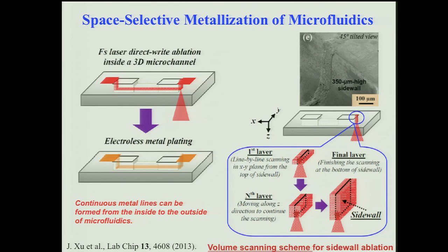We also developed a technique which can perform the space selective metallization of the microfluidics. This process consists of the femtosecond laser direct writing ablation inside the three-dimensional microchannel, followed by the electroless metal plating. As a result, the metal thin films can be selectively deposited on the glass roughened by the laser ablation due to the anchor effect. And in this process,